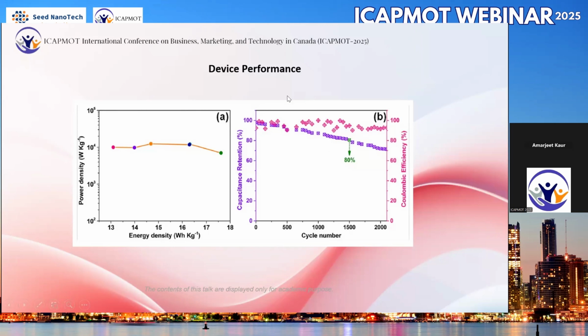Right now, we are working to improve its retentivity. Although we have achieved commercial grade values for the specific capacitance as well as the power density, the retentivity is just 2000 cycles. We are working so that it should at least go up to 20,000 cycles, and then maybe further up to 50,000 or 1 lakh cycles for the commercial application of this device.